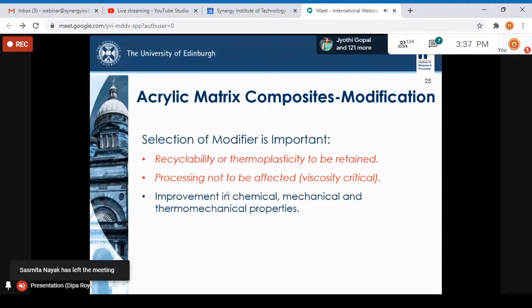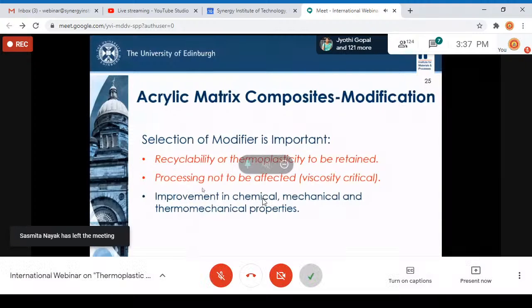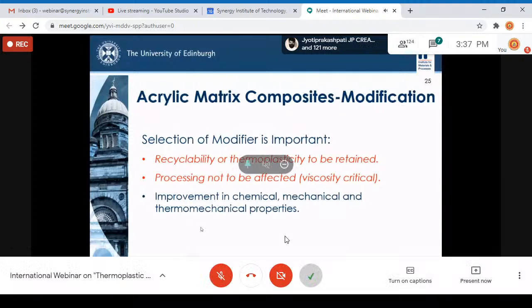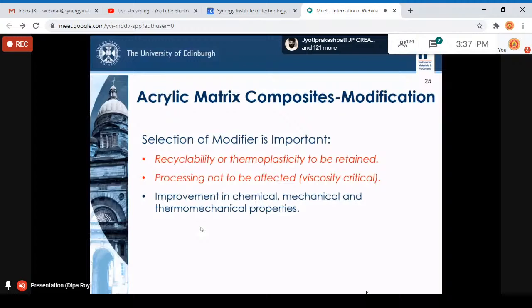We have to retain these two, and at the same time, we have to have some improvement in the chemical, mechanical, or thermomechanical behavior of the product. Now we selected a material, polyphenylene ether. We worked with SABIC actually. This PPE is from SABIC. We have some working relation with SABIC, so we got materials from them. And we selected polyphenylene ether with functionality. The functionality at the chain ends was very helpful in producing some reactive blending during the composite manufacturing.